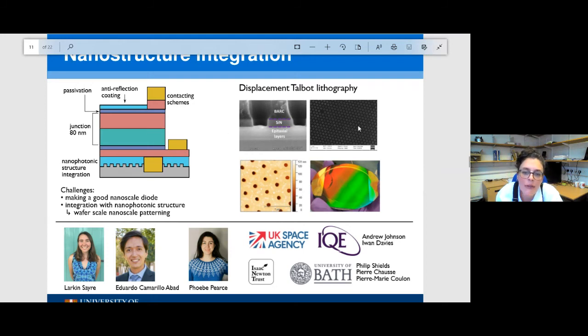So you can see here with the SEM images and the AFM, the patterns are not 100% perfect, but they're pretty good, pretty uniform, and they cover a full wafer. So that's a 4-inch wafer there covered with nanophotonic pattern, which is a really exciting thing to be able to do, because ultimately that's the direction we need to be going in. So we've been working with the University of Bath on this. The displacement Talbot lithography tool is their tool.